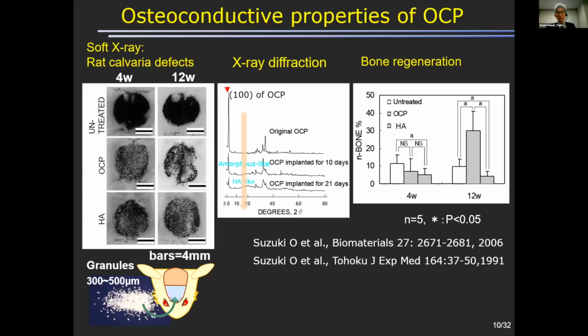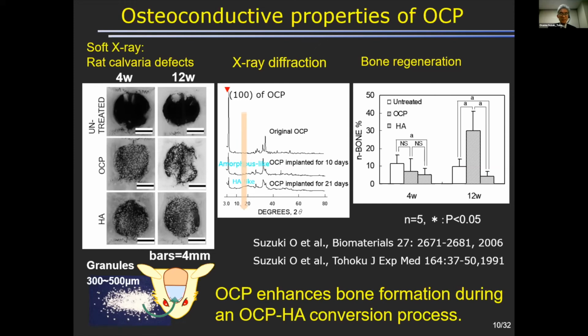This is an example of the characteristic OCP properties as a biomaterial. When OCP granules are implanted into a critical-sized calvaria defect, CSD, OCP enhances bone formation more than hydroxyapatite. And when we look at the crystal structure of OCP implanted in vivo, OCP is converted to hydroxyapatite progressively. So we concluded that OCP enhances bone formation during the OCP-HA conversion process.